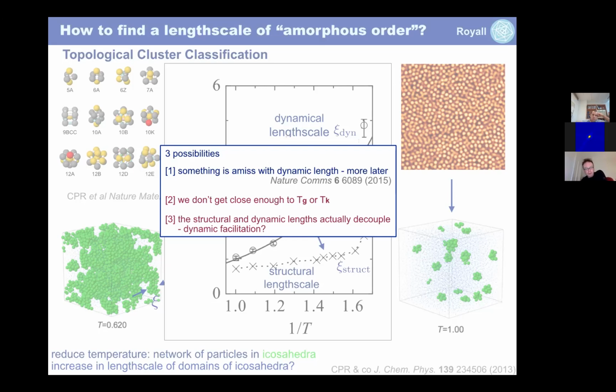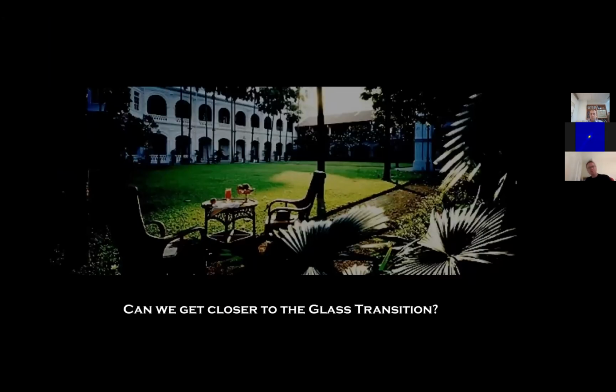Another possibility is that dynamic facilitation is actually correct. And we have this decoupling of the structural and dynamic lengths. Actually, because the structure doesn't matter in dynamic facilitation, then this is fine. So maybe just dynamic facilitation is correct. So the first thing we'd like to do is to get closer to the glass transition, and we can do this in the following way.